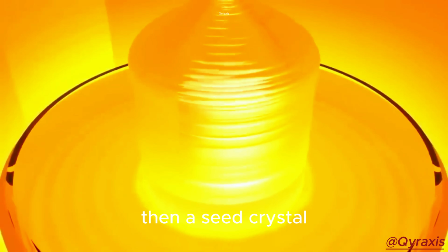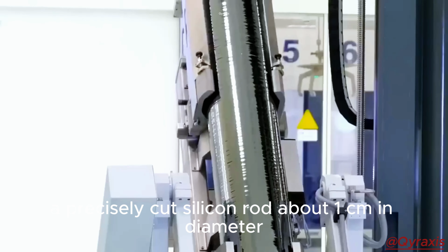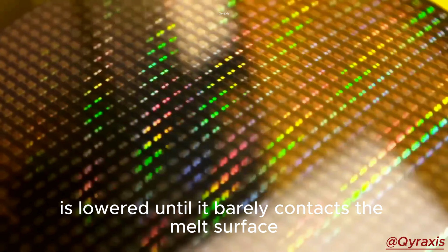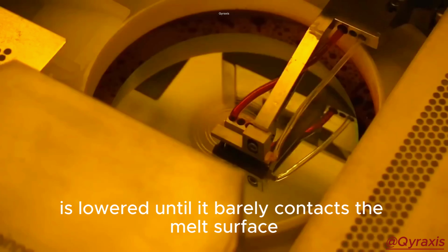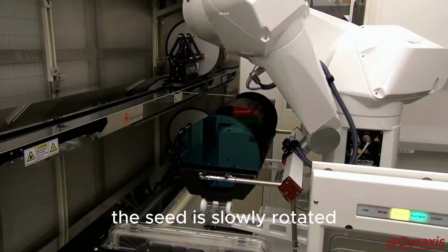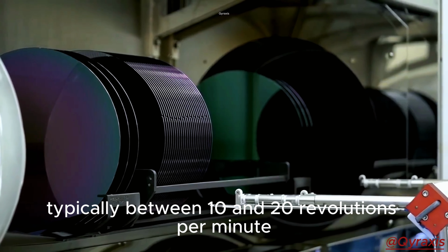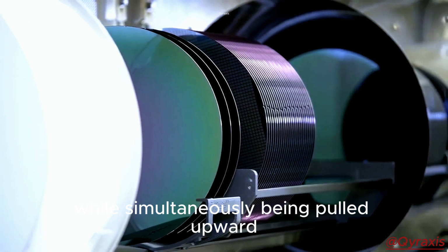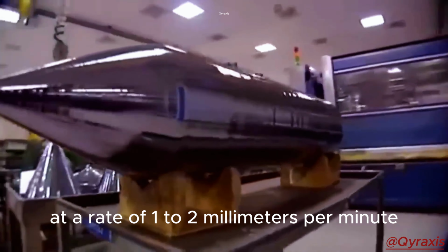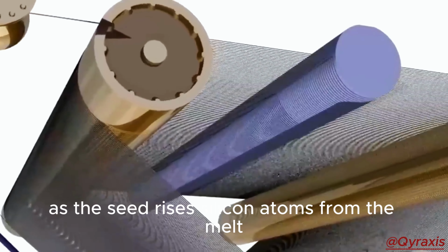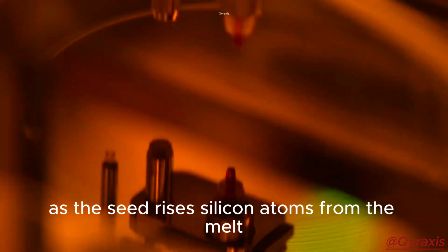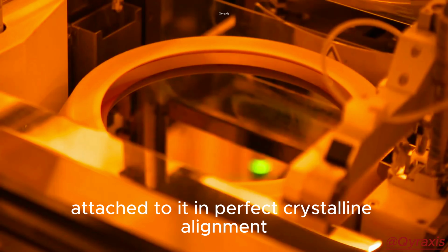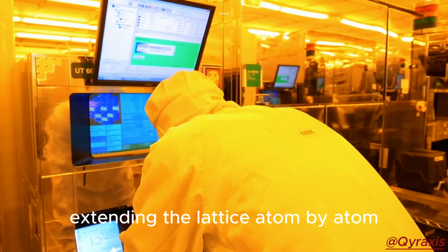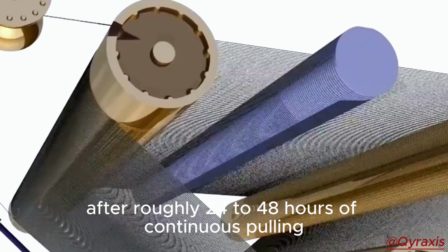Then a seed crystal, a precisely cut silicon rod about 1 centimeter in diameter, is lowered until it barely contacts the melt surface. The seed is slowly rotated, typically between 10 and 20 revolutions per minute, while simultaneously being pulled upward at a rate of 1 to 2 millimeters per minute. As the seed rises, silicon atoms from the melt attach to it in perfect crystalline alignment, extending the lattice atom by atom.